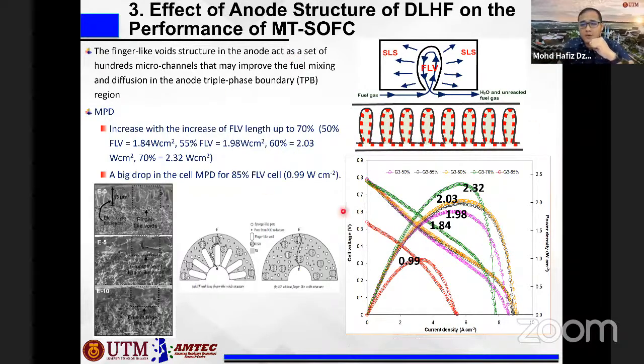So when you have 70% finger-like structure from the total cross section of the anode, you can further increase the power density up to 2.3 watt per centimeter square. This is actually the highest that has been reported in literature for a microtubular fuel cell.